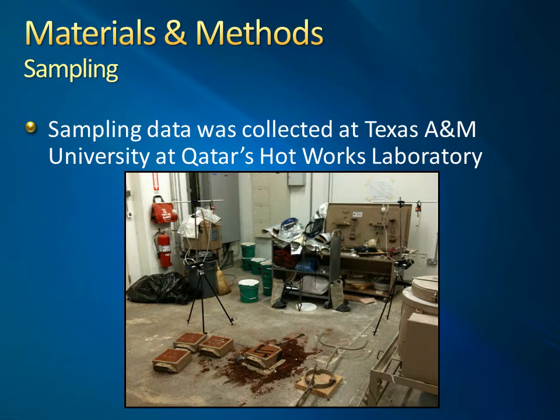The 3 sampling stands were placed on the 3 sides of the pour site, including directly next to the crucible furnace, with each stand holding a sampling pump and filter for the aluminum and silica assays. Since all aspects of the casting and finishing processes occur in this relatively confined area, the sampling arrangement sampled the same breathing air as the personnel and allowed the daily samples to act as replicate samples without interfering with the casting process. A field blank was collected for each assay during this period for analysis each day.